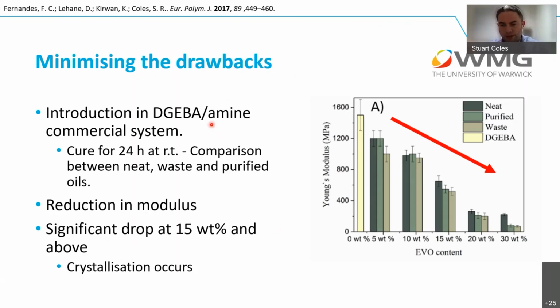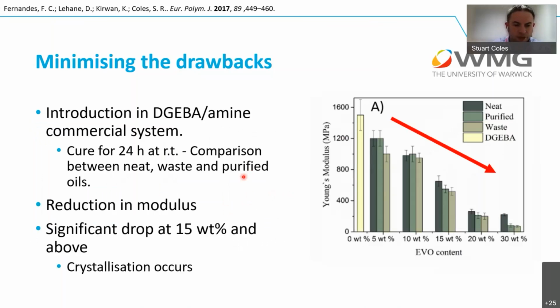So we went through all of these reaction stages and got this profile along. There was a significant drop at 15% and higher, and what we found was that we were getting crystallization of our polymer, and particularly the vegetable oil polymer was effectively no longer soluble within that epoxy mix. I haven't put the images in these slides, but you can quite clearly see visually at 15% the sample becomes very opaque very quickly, and that ties in with that drop in modulus as well. So the mechanical properties drop. We get effectively a biphase mixture of two different polymer types, and it doesn't blend very well. So within this particular system, 10% was about as much as we could really push it to.